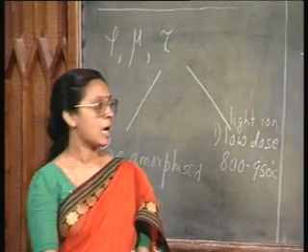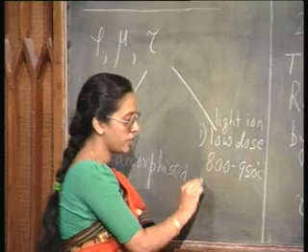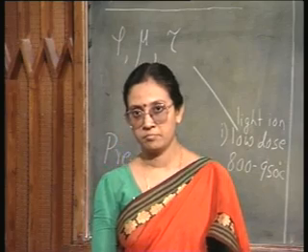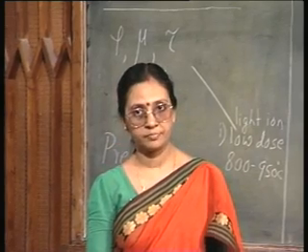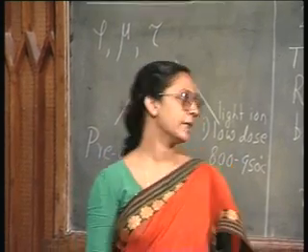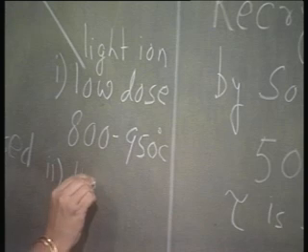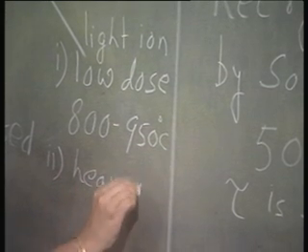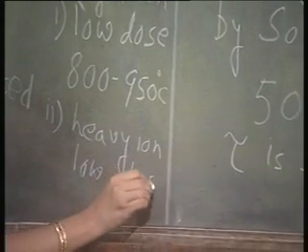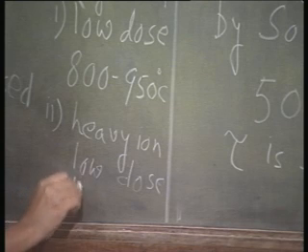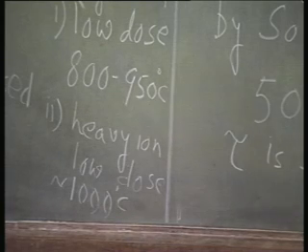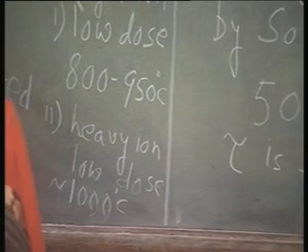Okay. However, if you have heavy ions, the situation is slightly difficult. Well, heavy ions still with low dose, you will get back about 1000 degree centigrade will give you recovery of all the parameters.